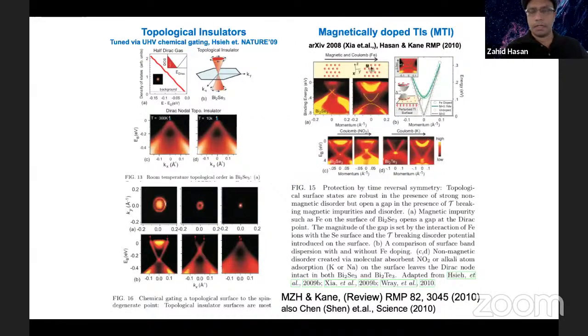Starting with topological insulator, you can try to put magnetic impurities on the surface or in the bulk to magnetize the whole system. And the initial theoretical expectation is that this will open a gap in the Dirac node, because now backscattering is allowed. So we wanted to probe that with spectroscopy. If we put magnetic impurities on the surface, what happens to the Dirac node?